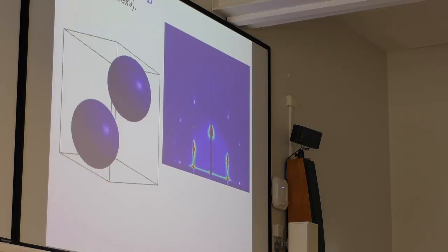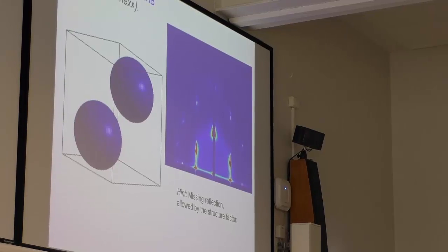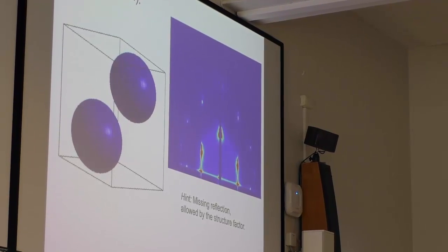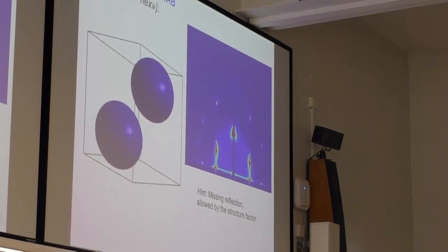right? You can see that there is some remnant intensity here, but it's almost gone. Whereas from naive calculations, you would have expected this to be a significant diffraction peak here. So what can the reason be for this? It is allowed by the structure factor I mentioned for you. The other factor that comes into play is the form factor.